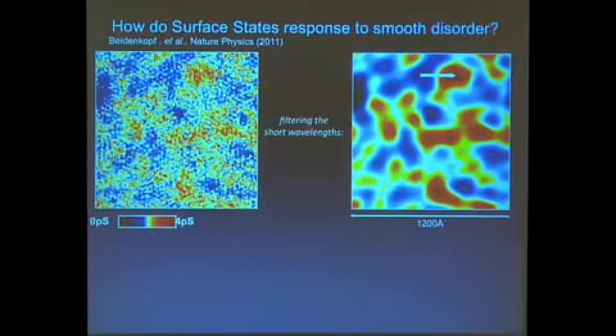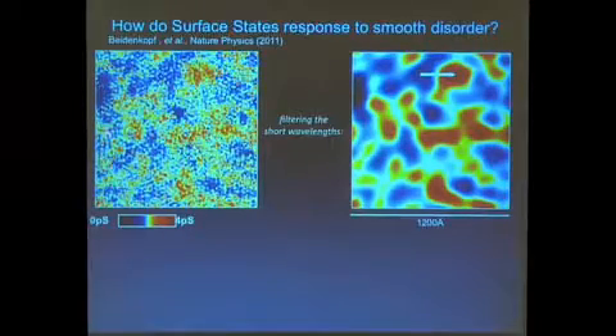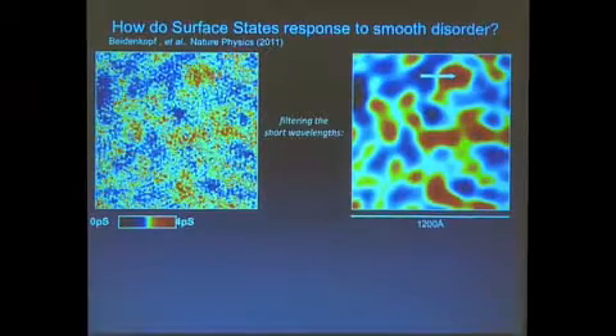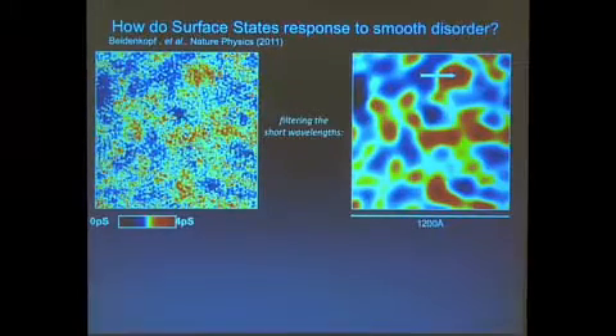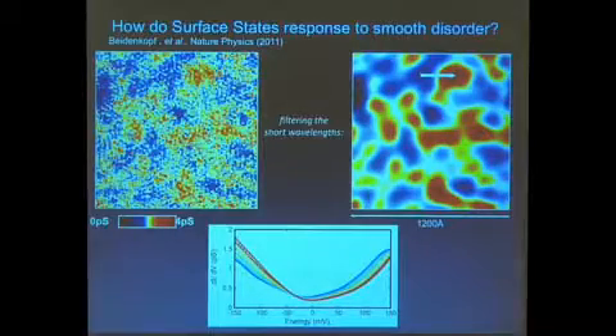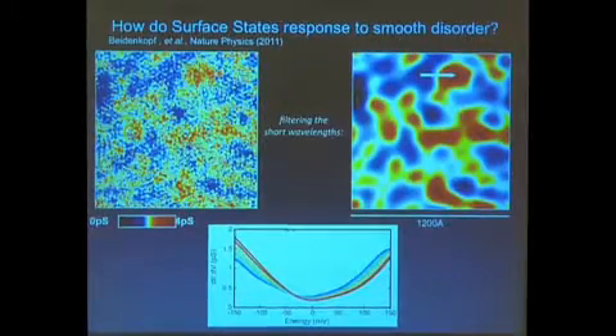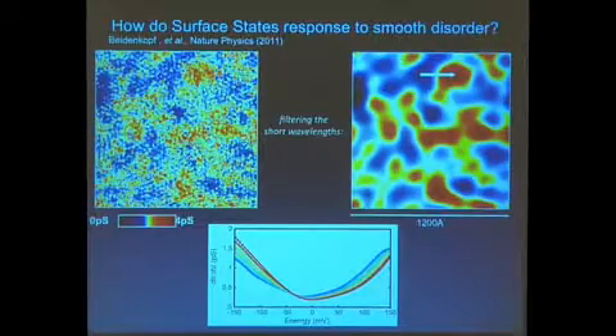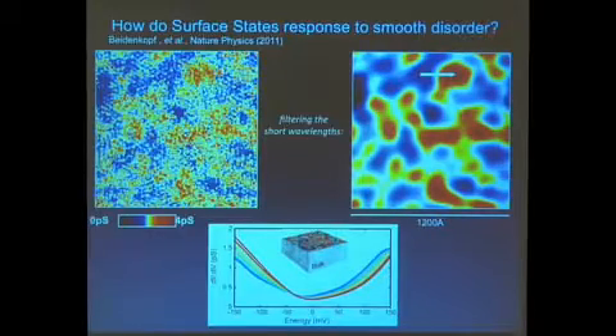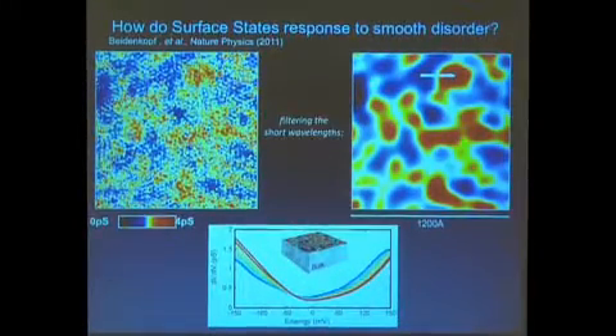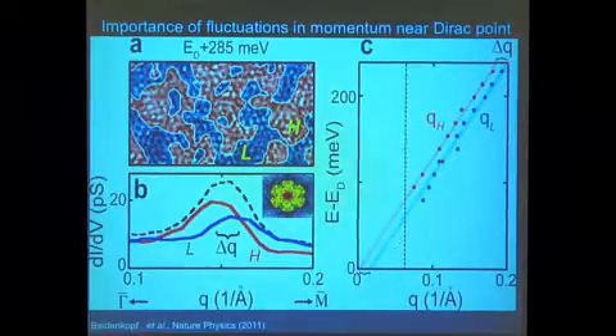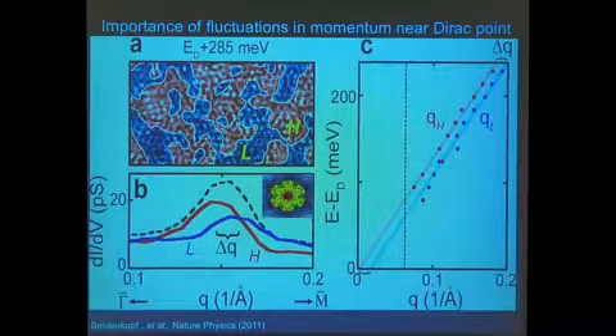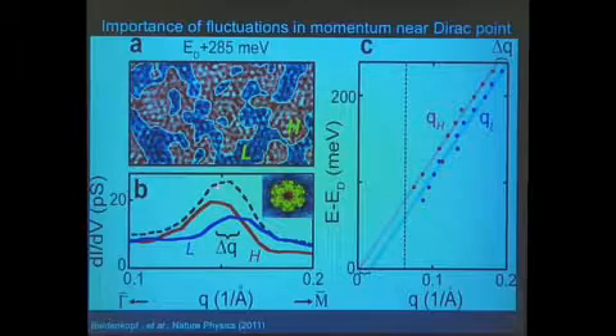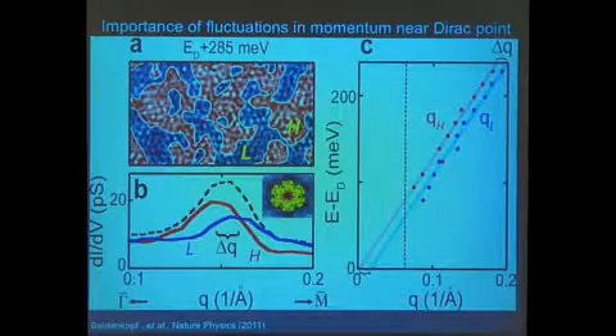But in fact, what you find experimentally is that many of these materials are basically doped semiconductors. Doped semiconductors have a situation in which you have fluctuation of the electronic band structure as you move around the sample, created by dopants. And you find that the whole electronic structure in the material is fluctuating in real space. And we find that the electronic states of the surface respond to this potential by changing their wave vector continuously as you move around the sample, basically riding this disorder potential having to do with the dopants in the sample. Okay?